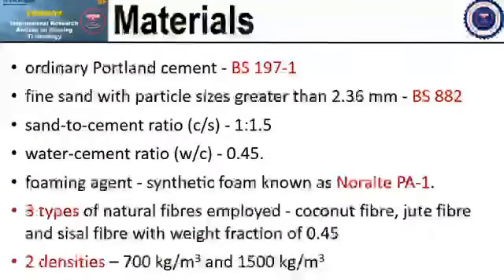Okay, the constituent materials that I used to produce the lightweight foam concrete comprise of ordinary Portland cement, or cement CEM I, conforming to BS 12 and conforming to BS 1971. Then I used a fine filler of fine sand conforming to BS 882 with particle sizes greater than 2.36 mm obtained through a sieve process. A sand to cement ratio of 1 to 1.5 was used for all the mixes, while the water cement ratio was kept constant at 0.45.